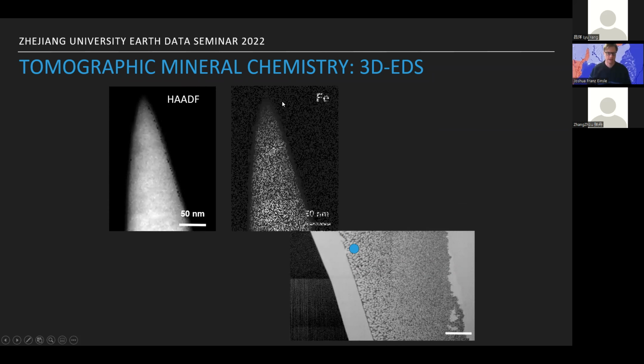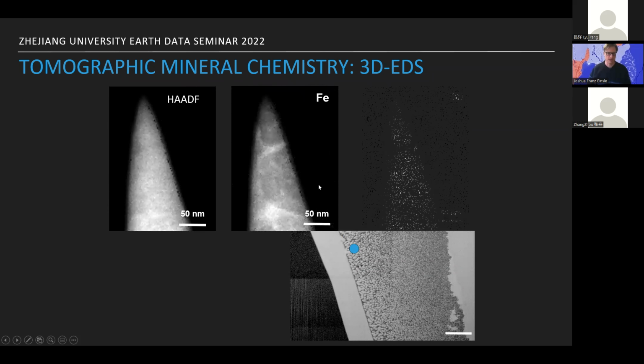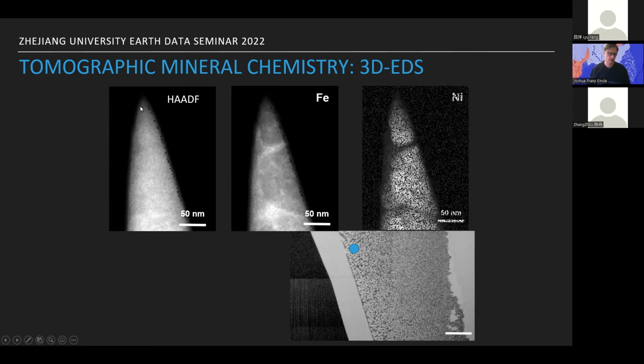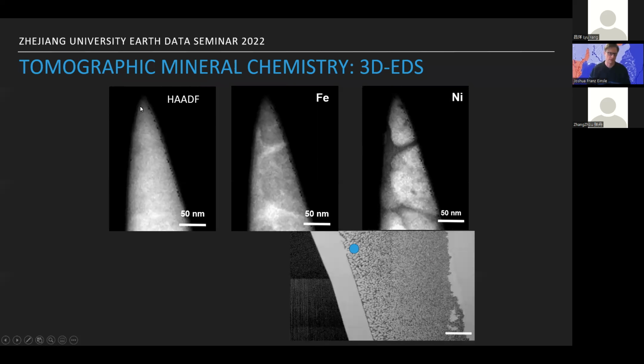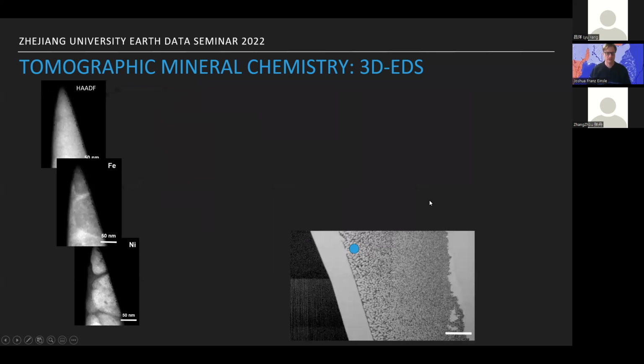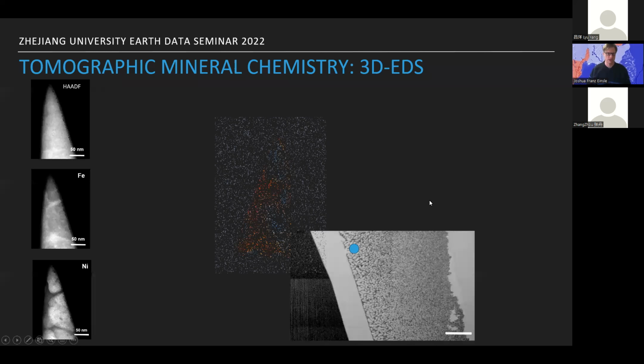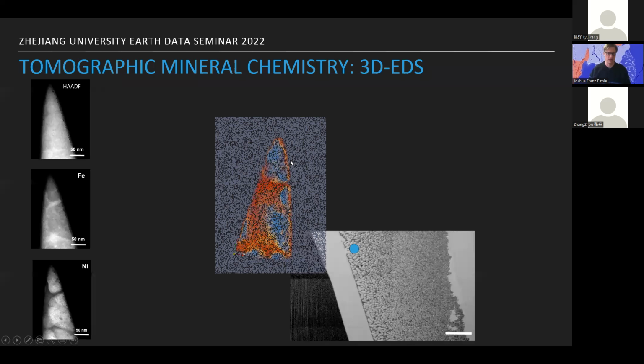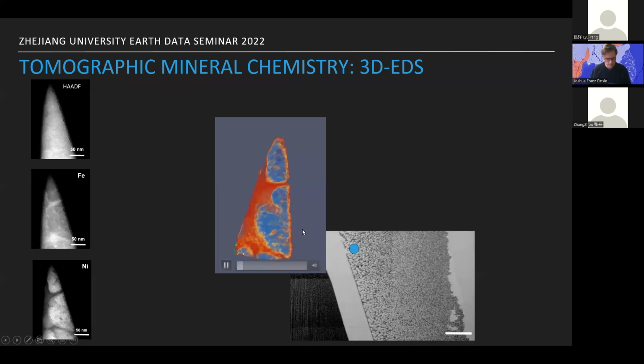And from that sharp needle, you can see that if I use scanning transmission electron microscopy in the diffraction contrast, it's all very similar because, as we said, compositionally the two phases are very, very similar. However, if we look at it chemically, we can see good separation in iron and nickel. So now we take a tilt series, and we can reconstruct into 3D these two phases, and we can see very good separation of the two phases.